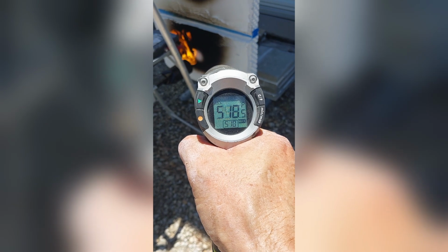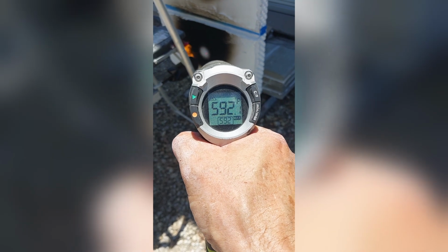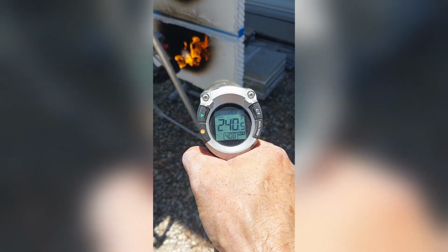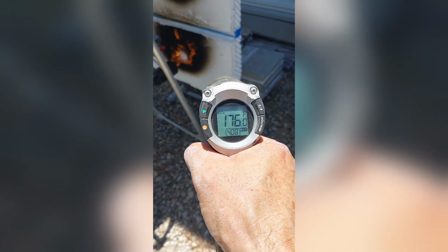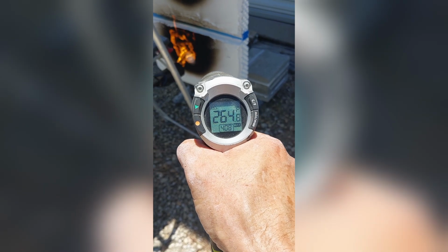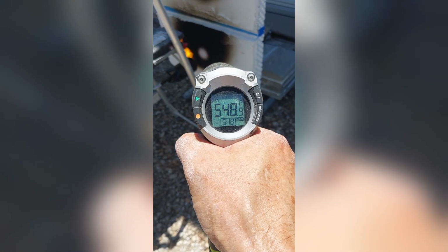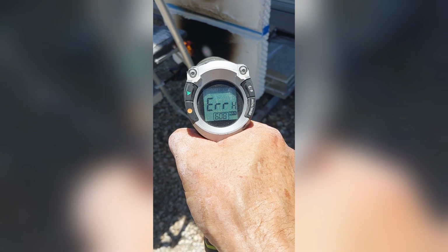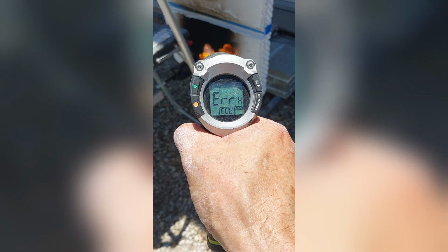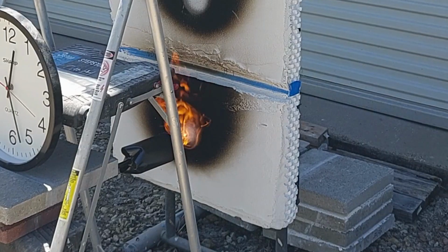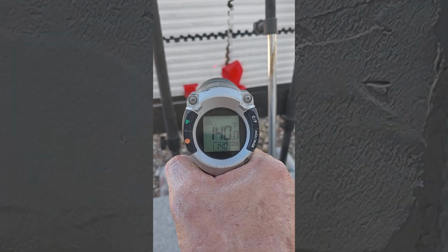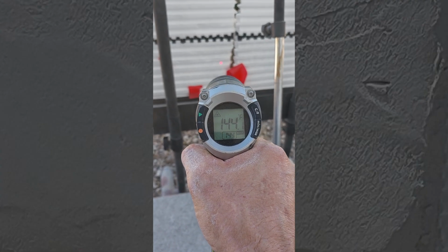At the 2nd hour mark, the temperature difference between the intense hot center surface, the white spot, and the outer edge of the test surface is significant. Our digital infrared temperature instrument measures up to a maximum reading of 600 degrees Fahrenheit and displays an error code beyond that level of heat. As we move to the rear of the panel, the flame in the front continues to burn above 2000 degrees Fahrenheit. As we touch the back of the styrofoam panel, it feels surprisingly cool.